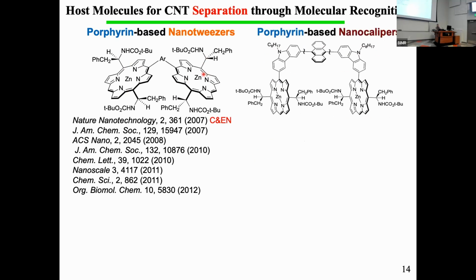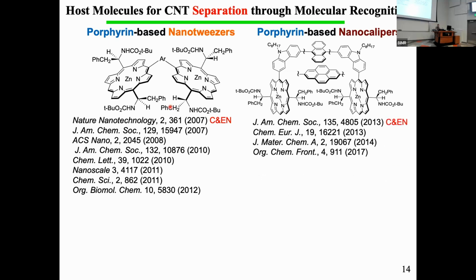And this is the second generation of the host molecule, called porphyrin-based nanocalipers. The characteristic of this host molecule is that the two porphyrin units are aligned in parallel. And it has a wider, bigger, or deeper cavity as compared to the nanotweezers. We expect more precise structure discrimination ability based on this nanocalipers. Of course, we can tune the distance between the two porphyrins. That's why we call this nanocalipers. And these are the publications.